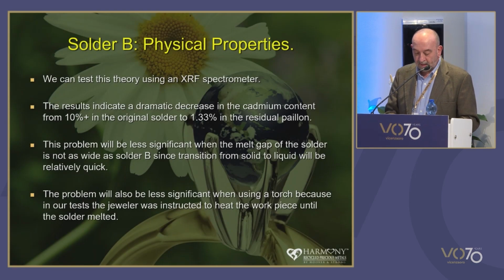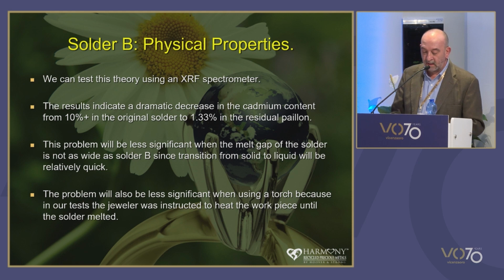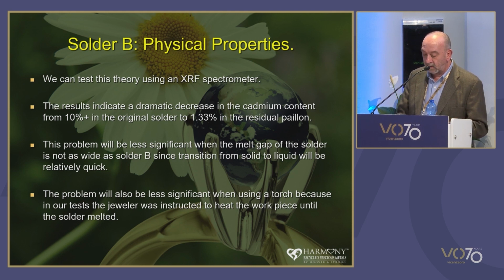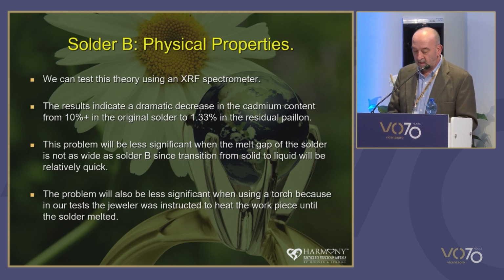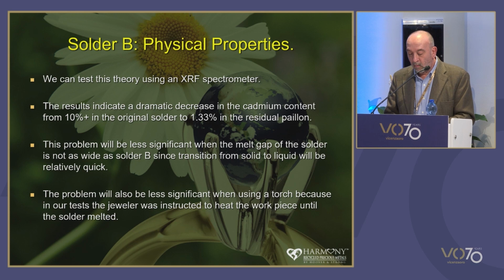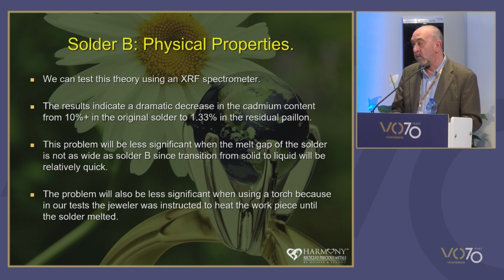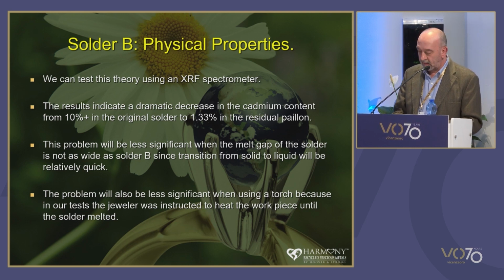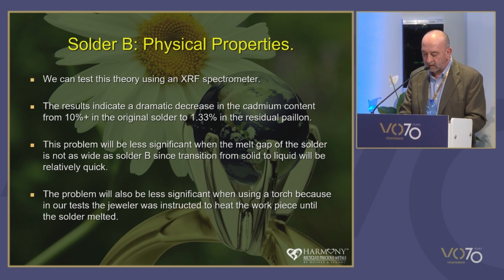So we gave this a quick test and we did some analysis on the residual piece of solder that was left in one of the solder B tests. And typically the solder's made up with 10% cadmium. But when we tested the residual piece, it only had 1.33% cadmium in there. So we believe this loss would raise the melting range of the solder above the furnace temperature.